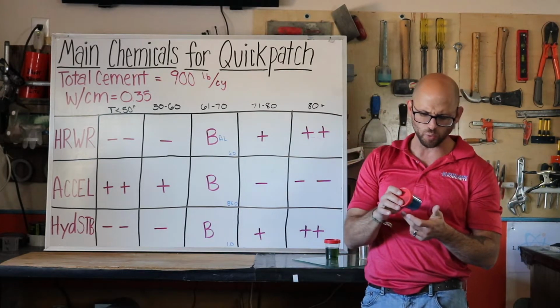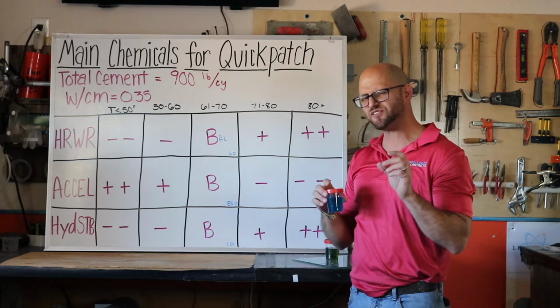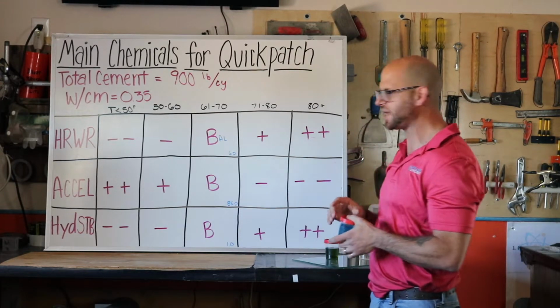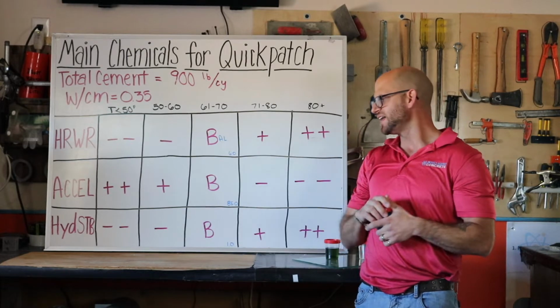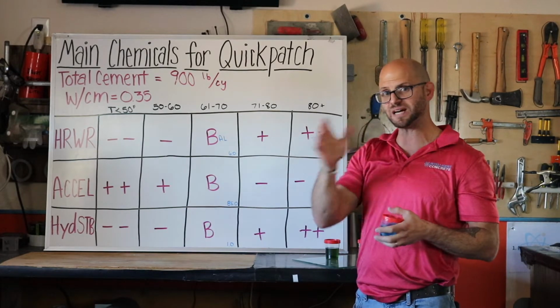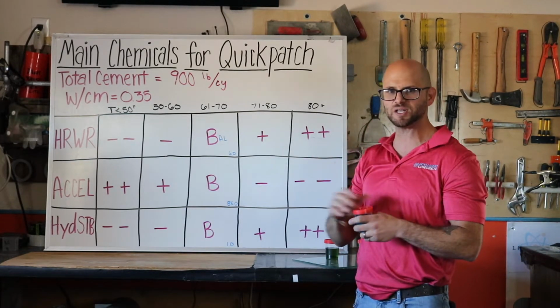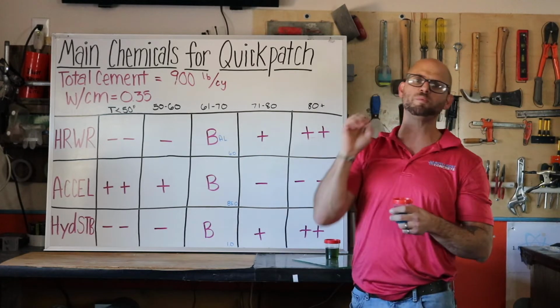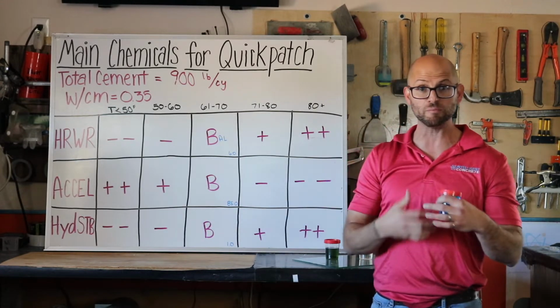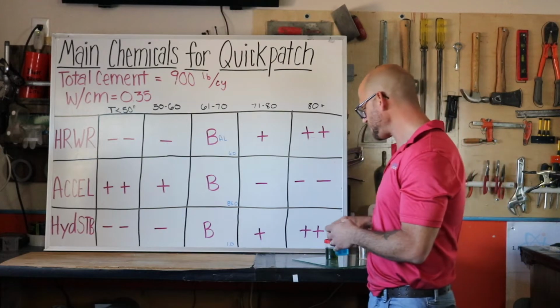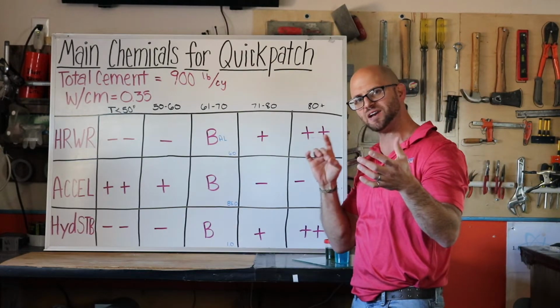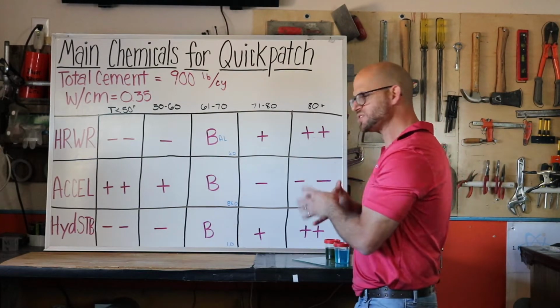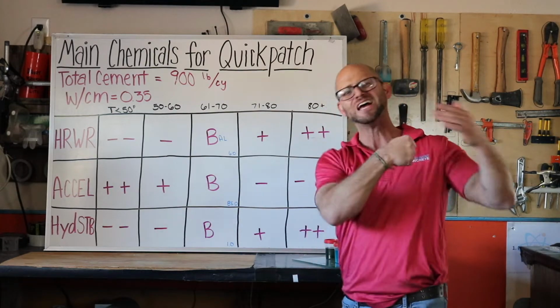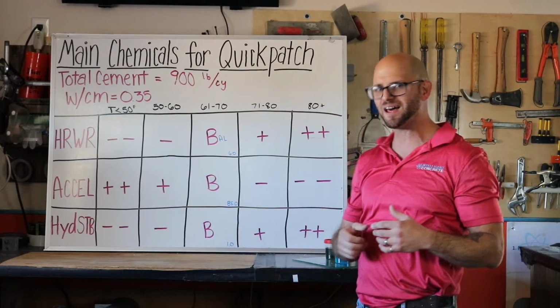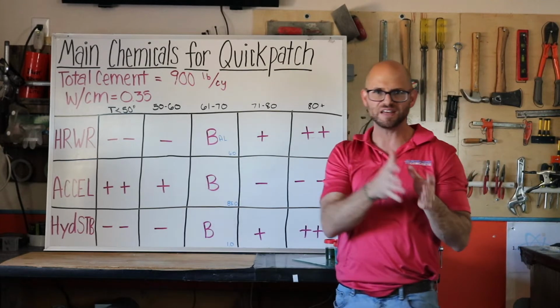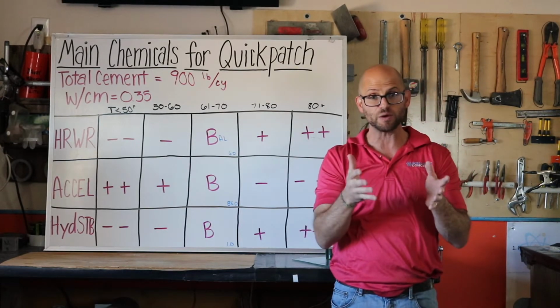I believe this is called the 125. I use this at a very, very low dosage rate. I'm trying to hold back not only that slump retention, getting my slump life out of that 60-minute drive, but also hold back that acceleration period so I can get more dissolution out of my cement particles and really hold back that energy so that when the hydration stabilizer stops working, that acceleration takes off like a bat out of hell and we get those strengths at that very short window that we need and that we want.